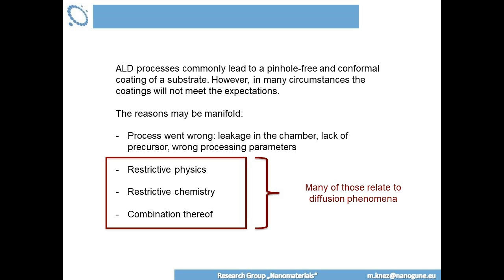And of course, this can have several reasons. And one, of course, is the normal reason that something went wrong, so your process doesn't work properly, because of your precursor delivery system, because of your chamber temperature, because of non-homogeneity, and so on. So you can check this very easily from the engineering aspect. But you have also to deal with the physics and the chemistry and the combination of those two if everything else from the engineering aspect works well. And many of those things are really related to diffusion issues which you may encounter during your processes.